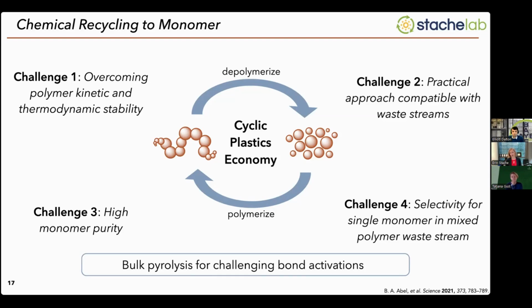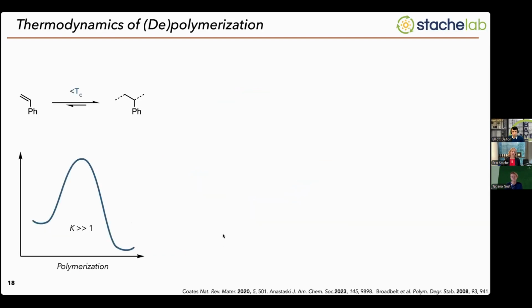Could we use bulk pyrolysis to activate these bonds and break down these polymers back into their constituent monomers? So the thermodynamics of polymerization or depolymerization, since it's just the reverse process, if we think about something like polystyrene, this polymerization occurs through enthalpic driving force, right? We go from a carbon double bond to forming a new carbon single bond. And so this polymerization is very enthalpically driven, thermodynamically downhill. Once you start this polymerization, it'll go all the way to the polymer and it will stay there.